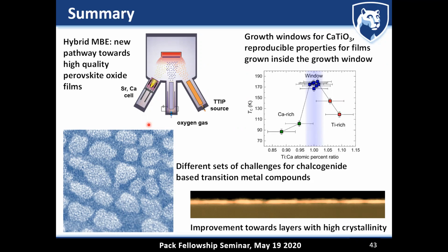Okay, so this is an excellent question, and you must have recognized I'm not showing mobility data because I wanted to look good. So it turns out that the theoretical limit of mobility is on the order of 200 centimeters squared per volt second. We are hovering about 1 right now. So this looks like a slow start. And what I personally believe is that the reason for this limited mobility is actually coming from these twin boundaries. So the task is to be able to drive out these twin boundaries.